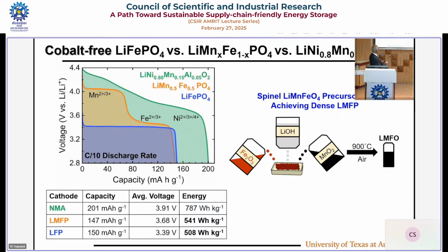We make a spinel first by high temperature. Take manganese oxide, iron oxide, heat it, you have a good spinel where manganese and iron are bonded next to each other. Good solid solution, no problem. Then you treat with phosphoric acid or ammonium hydrogen phosphate, lithium carbonate, then you get the material. That material is amazingly dense.